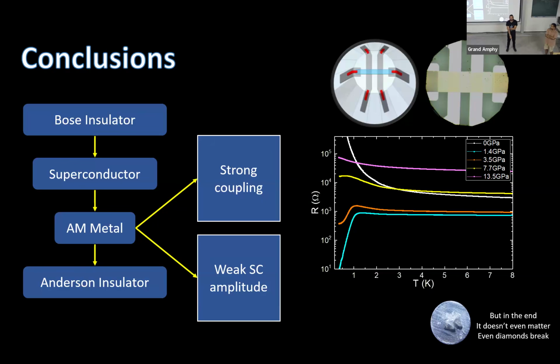Okay, because it's cut. Because the machining of the diamonds is super precise. If you have a bit of a degree of unflattened area between your diamonds, one diamond will break the other. It's very easy to break diamonds. This is how the diamond looks after the experiment. You don't see the diamond at all after fully taking the diamond to the edge. So yeah, you need to be very, very precise in that machining. Okay, for artificial diamond, the surface is very rough, but perhaps the natural one is good.